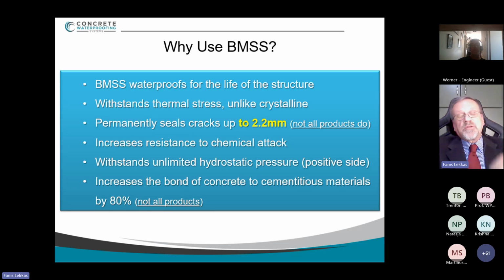It's just like trying to take sugar out of a cake. After the cake is out of the oven, it's impossible to take the sugar out anymore. On the contrary, the gel will stay there, protecting the structure from water and soluble chlorides and sulfates for the life of the structure. I've already talked about withstanding thermal stress, and the crack sealing ability, the static crack sealing ability of this technology can even reach up to 2.2 millimeters. Well, naturally, not all products will do that, but they will seal static cracks, okay?